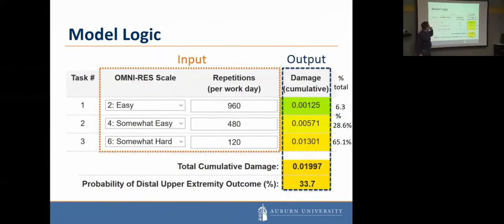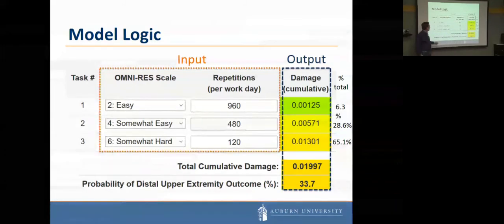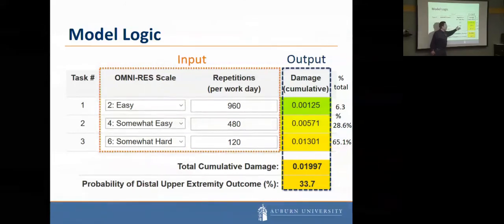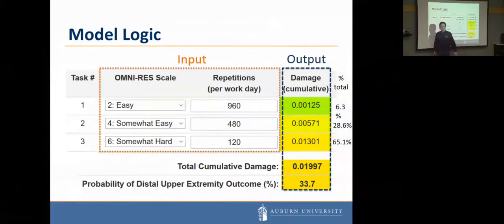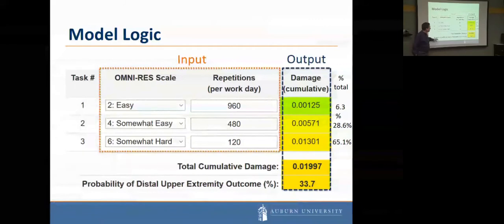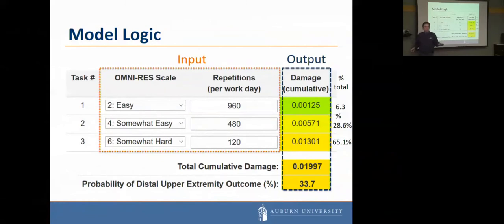So in a similar manner to the lift tool, we would first pick a level of perceived exertion on the scale. So this is an easy task. Say we did 960 repetitions. This would be our cumulative damage. In this case, the first task would be associated with 6.3% of the total damage. We had a somewhat easy one. We did 480 of those. That would account for about 28.6%. And we did some somewhat hard ones. We did 120. That accounts for 65% of the total damage done during the workday. In total, we would have about a 33% risk of injury.